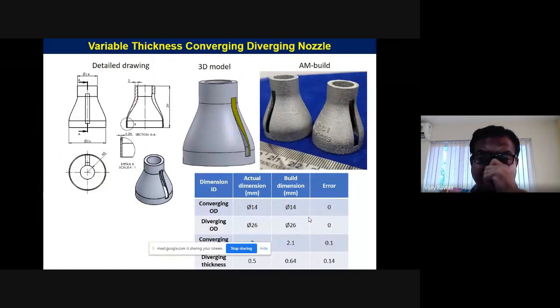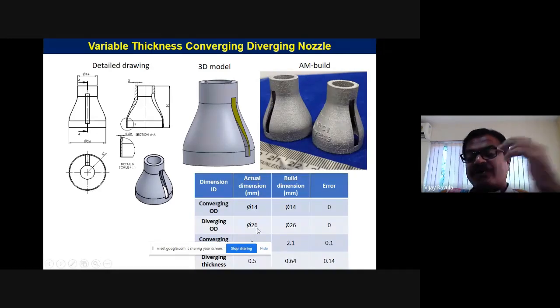And variable thickness converging-diverging nozzles, especially in missile applications or space launch vehicle applications, you cannot make this kind of thing by the conventional process. We made a 3D model, and you can see the thickness comes down and then goes up, because it has to withstand the pressures and other loads. We have a 14 mm converging OD, and the diverging OD is 26. We could design and build it with very small tolerances. The actual thickness dimension is 0.5 and the build dimension is 0.64 on the diverging side. So it is very thin, and we are also saving material.